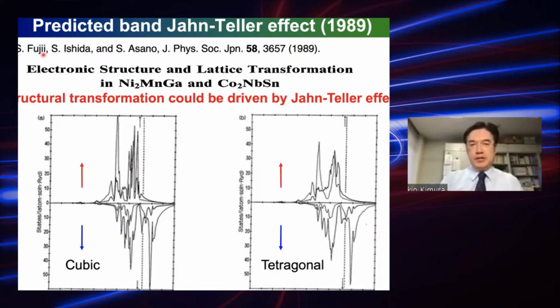There was a prediction for the structural transformation, which could be driven by the Jahn-Teller effect. As you can see, there is a sharp peak at the Fermi energy in the minority spin channel, which can be a driving force of the lattice instability. Actually, in the tetragonal phase, the calculation shows that there is a splitting at the Fermi energy. This kind of electronic structure could be the underlying mechanism of the Martensitic phase transition and the Martensitic phase.